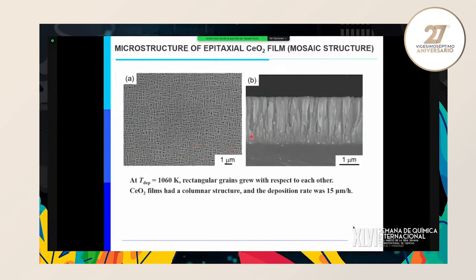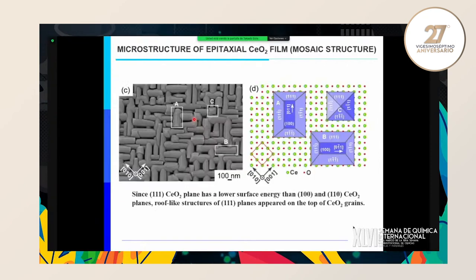So in order to make very good YBCO epitaxial film, we have to make a good epitaxial ceria film underneath YBCO. Ceria is cubic and almost all grains are rectangular, almost perfectly aligned at right angles, as you can see here. So in XRD, it is the same as single crystalline. We call this a mosaic structure. It's polycrystalline, but looks almost like single crystalline. This is a more detailed structure of ceria. Ceria 100 is parallel to the substrate. The side plane is 111. This structure cannot be distinguished from single crystalline. It is basically single crystalline.